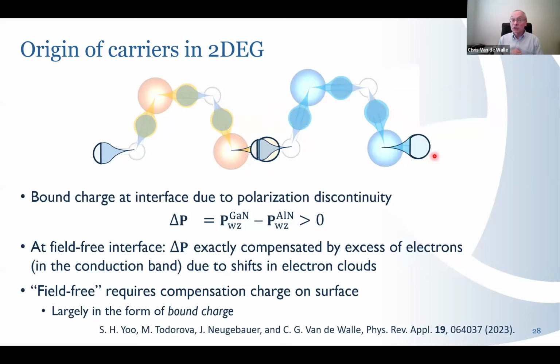The surface states are not the source of the electrons. They are basically a sink for electrons. If you have surface states, they will drain away some of these electrons that in principle could be present in a density as high as the polarization discontinuity, but some of them will drain away to the surface, and preventing them from draining away will enhance the 2DEG density, okay? And in order to address that, you need to worry about the structure of the surface. There is compensation charge on the surface, bound charge, etc.